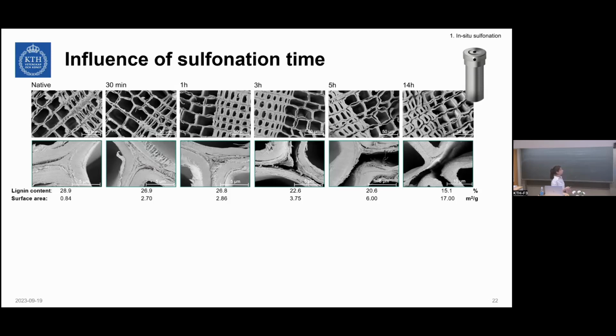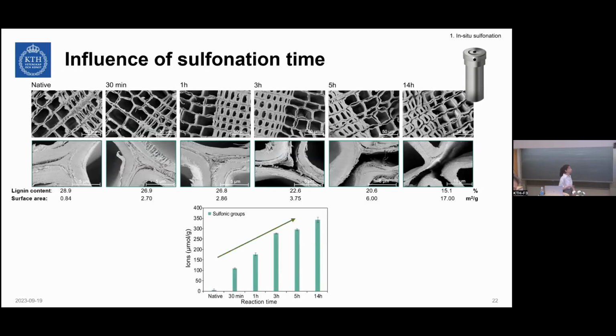In a similar way, we could also see the increase of the surface area as we're creating more porosity and empty spaces inside the wood structure. From a chemical point of view, we could see an increase of charge groups. In this case, it is sulfonic groups, up to around 350 micromole per gram, the longer we push the sulfonation step.